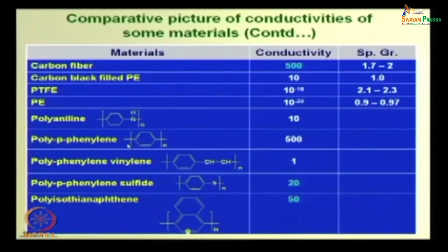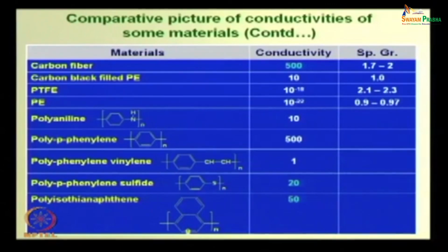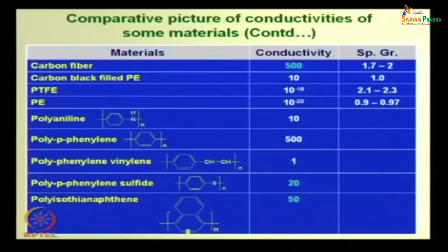Then you take that emeraldine salt, put it in some base, means ammonia solution. So, it will be converted to base form, means HCl is removed from there. Now, that base form is soluble in organic solvent, but the base form is not conducting.